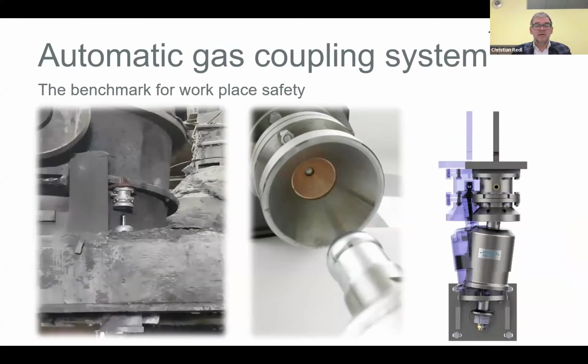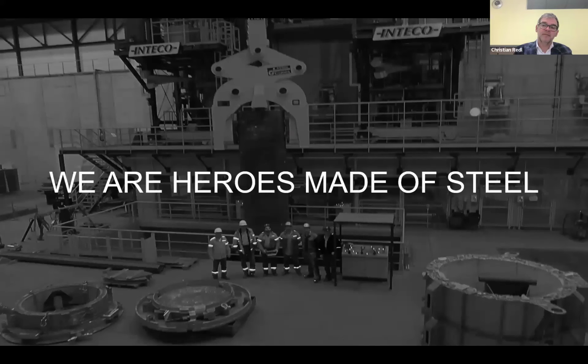So coming to an end, let me show you an automatic gas coupling system. As I said, the degassing efficiency is very much dependent also on a very good stirring of the melt through the porous plate at the bottom of the ladle. And for this, we've developed this automatic gas coupling system, where I simply put the ladle on this coupling device. It couples automatically. It has metallic sealing, very highly resistant, therefore also suitable for the tank degasser. And once again, you remove any manual worker from the area close to the ladle.